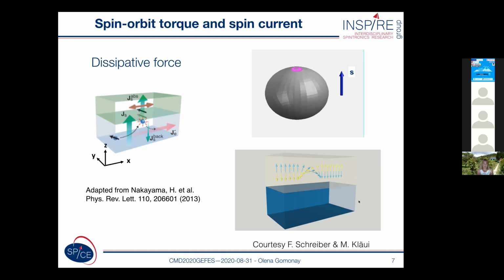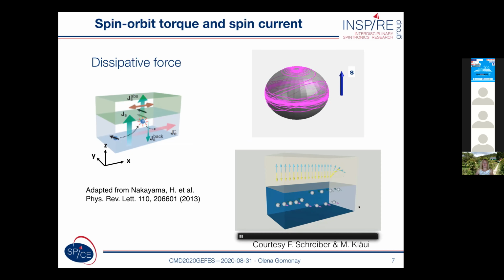Such torques can induce dynamics of the antiferromagnetic vector. So in the right upper panel, you can see now the dynamics of the Néel vector, the trajectory of the Néel vector on the unit sphere induced by the spin current with the polarization shown with this blue vector. So you see the spin current can induce rotation of the Néel vector. As well, the spin current can act on the textures, the domain walls, and it can induce the rotation of the Néel vectors and domain wall motion.